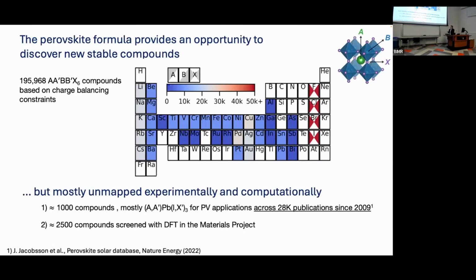But even in that chemical space, the formula is largely like this. We have a couple of choices for the A site cation. This can be organic or inorganic, typically organic. And the B site cation is limited to lead. Plus, there's a halide that's iodide plus some other mixture. So there's a really constrained formula, and the majority of this investigation in the field has been trying to find different combinations of cations, organic or inorganic, and doping or mixing some additional halide with iodide. So even though it's 1,000 compounds, it's largely limited to a very narrow chemical space.